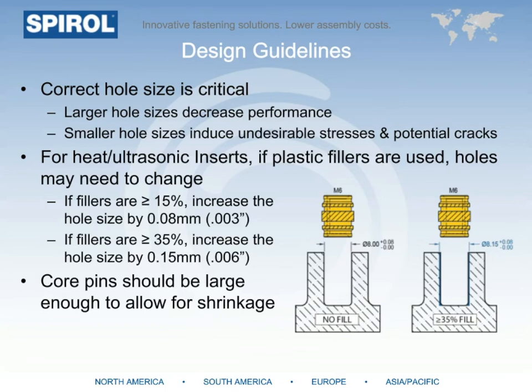However, if the same component was nylon 6/6 with 35% glass fill, we would adjust this initial 8 millimeter hole recommendation up by 0.15 millimeters and then apply that 0.08 millimeter tolerance. The core pin used to mold the hole should be large enough to allow for the plastic to shrink down once cooled and conditioned.